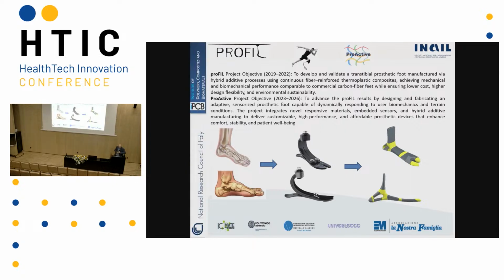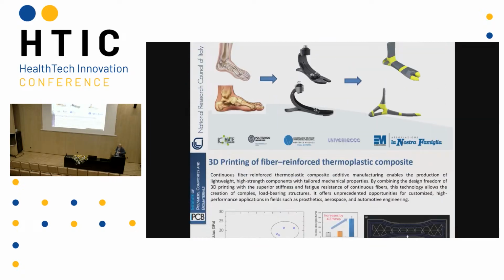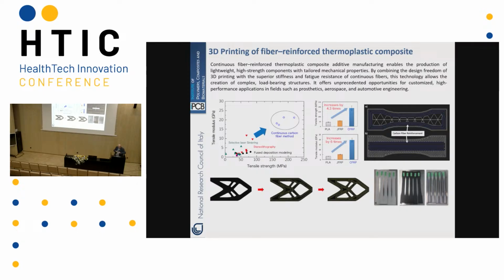This is another project in which we want to demonstrate that it is possible by 3D printing to obtain a device, a prosthetic foot, that is used in normal life by people with a high level of activity. It means young people. In this field, the level of activity is K1 for elderly, and K4 is the maximum activity, or athletic activity. We are here in the field of K4, for people with a weight in the order of 80 to 100 kilograms, so very important performance is needed. We want to demonstrate that by 3D printing it is possible to do that and obtain the same performance in terms of biomechanical behavior of this object. To do that, we have to use a continuous filament fiber 3D printer.